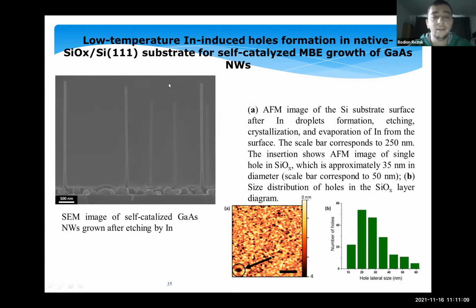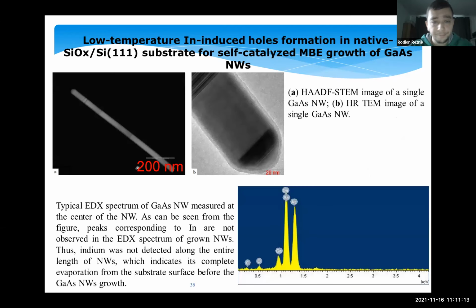and length of nanowires, which is important. There is no peak in our EDX corresponding to indium, and so it means that we fully evaporate indium from the substrate.